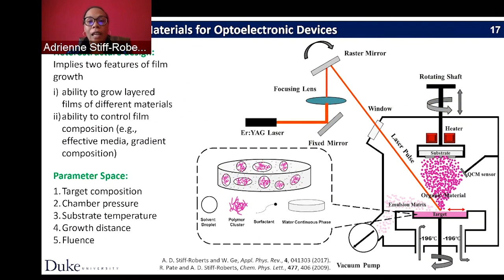Then the other thing that you do in inorganic systems like MBE all the time is to grow a film where the composition is determined by what you deliver to the film, and so the function of the film is determined by the composition. That's difficult to control in a polymer-based system like the polymer with the inorganic nanoparticles, because when you blend those materials in solution, they want to segregate into different phases. They don't want to blend nicely. But MAPLE allows us, because of the process, to control the blending on the nanoscale because of the way the materials are delivered to the substrate.